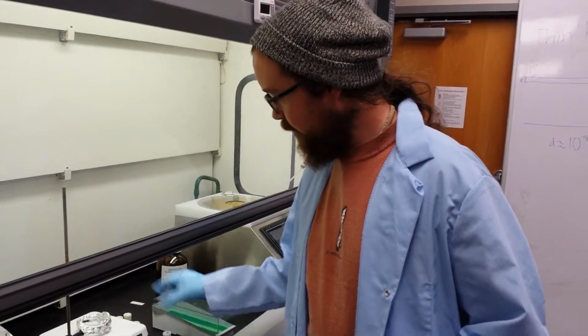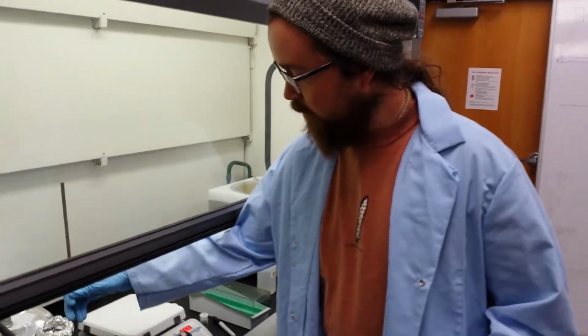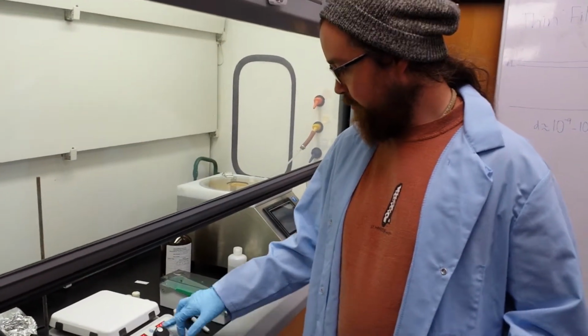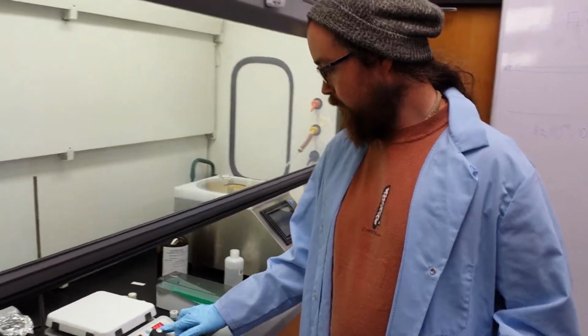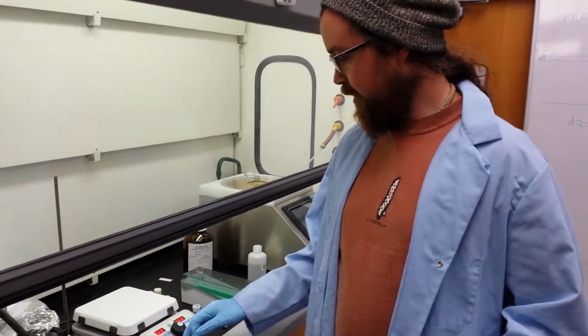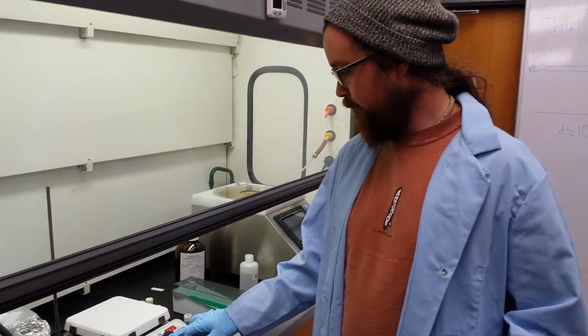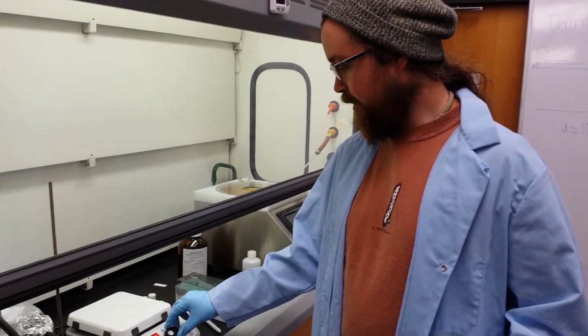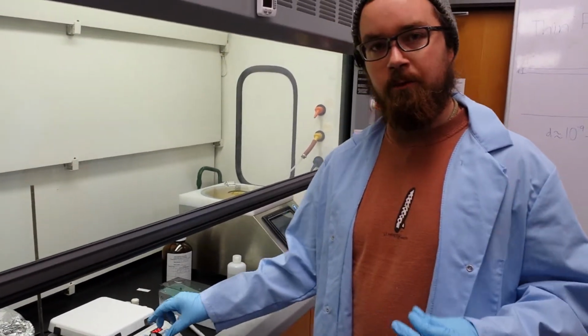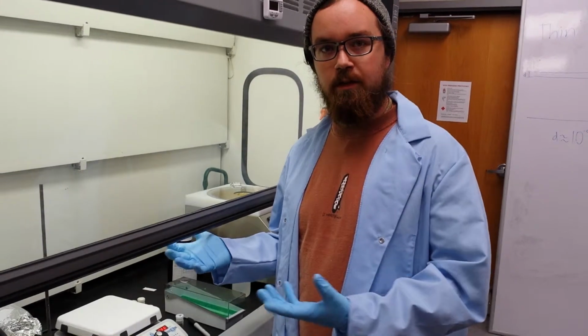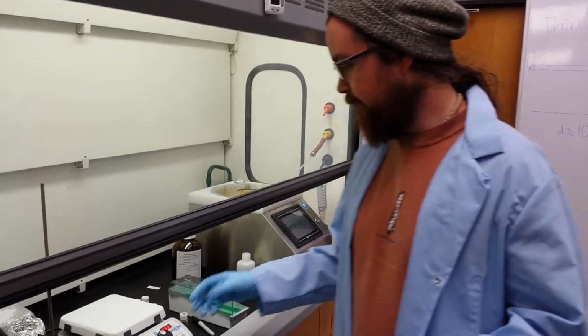So now we're going to go ahead and actually make a thin film. The first step in this is we want to turn the stirrer off, and then we want to turn the heating on, because when we make these films, since they have liquid in them, once we deposit them, we want to heat the film up so that the liquid can evaporate off and we just have solution left.